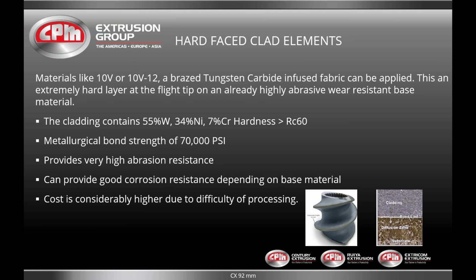The hard clad elements, materials like 10V and 10V12, which are already a hardened tool steel or martensitic stainless steel in the case of 10V12, a brazed tungsten carbide infused fabric can be applied. This provides an extremely hard layer at the flight tip on an already highly abrasive wear resistant base material. The cladding contains 55% tungsten, 34% nickel, and 7% chrome. It's got a resultant hardness of Rockwell C greater than 60 and a metallurgical bond greater than 70,000 psi. The cost is considerably higher, though, due to the difficulty of manufacturing.